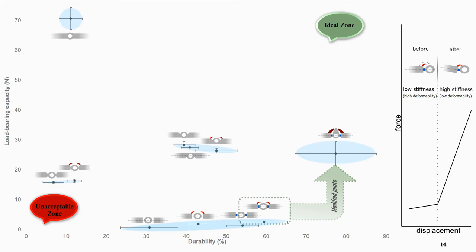Furthermore, spikes had a notably higher influence on the load bearing capacity of the flexible joints compared to the half-fused and point-fused joints. This was because the half-fused and point-fused joints failed prior to their spikes activation. Both these two types of joints and fully fused joints, which had a direct connection between their veins, failed either by brittle fracture or plasticity before their maximum displacement was reached.